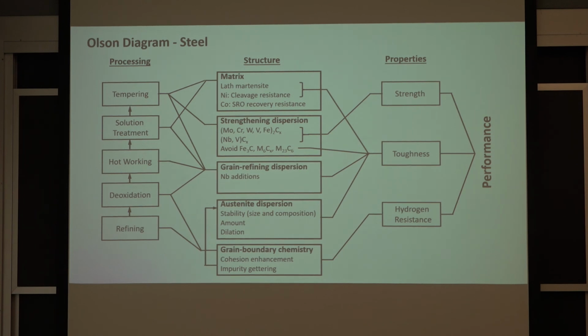I've seen this in action a couple times working on structural steels for wind turbine towers. By putting niobium in, you can very effectively increase strength. You can reduce the grain size, from my experience, from maybe 100 microns down to 10 microns. And that increases the strength while also increasing toughness.